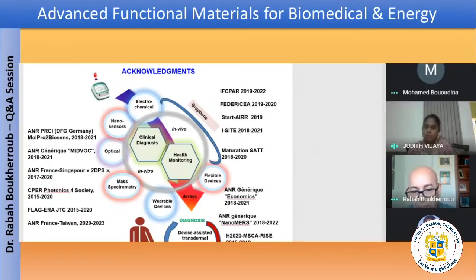Second question. Can we prepare graphene using the chemical vapor deposition method? CVD, yes, but then you have to be equipped. There are many laboratories growing CVD graphene, but you can buy it as well. The same for chemically derived graphene. For CVD, I think that's not an issue if you're equipped. But the problem is mostly for chemically derived graphene because it's not a reproducible process. The way you oxidize it and the way you reduce it will affect a lot of the properties of the end material. But CVD is no problem. It's very nicely controlled. It's a very known process, and there are very specialized laboratories for that.